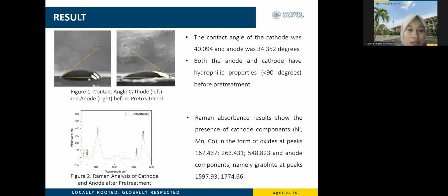For the test result after pretreatment, namely with Raman spectrophotometry, the peak values obtained at 167, 263, and 548 indicate the cathode, and 1597 and 1774 indicate the anode, namely graphite with G and 2D bands, and no binder peak was found at a wavelength of 800, which indicates that pyrolysis can remove the binder and restore the surface properties of the mineral to their original properties.